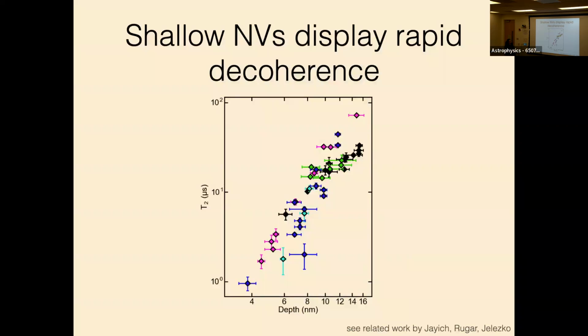So one of the ways that we know this is that you can just look at individual NV centers and look at their coherence time as a function of depth. And I told you earlier that you can get to coherence times of many milliseconds at room temperature. And that's true if you're around 100 nanometers or a few hundred nanometers away from the diamond surface. But once you get very close, we see this horrible sort of roughly 1/4 power law scaling, such that when you're within, let's say, 5 nanometers of the surface, people see sub-microsecond coherence times.